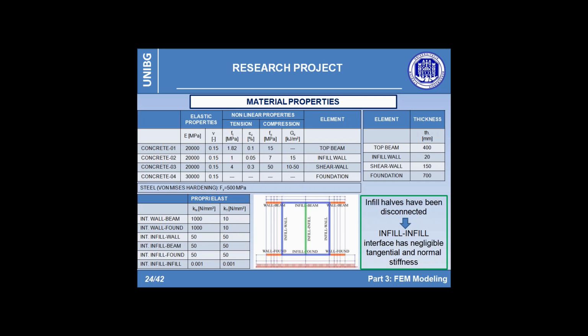For the same reason, the ultimate tensile strength and strain have been hypothesized to obtain a tensile fracture energy more similar to that of a traditional plain concrete. Moreover, concerning the behavior in compression, the value of the fracture energy is very difficult to calibrate, affecting in a very strong way the ductility capacity offered by the structure. Despite that, it results that values between 10 and 50 kilojoule per square meter can be suitable to describe the experimental results.